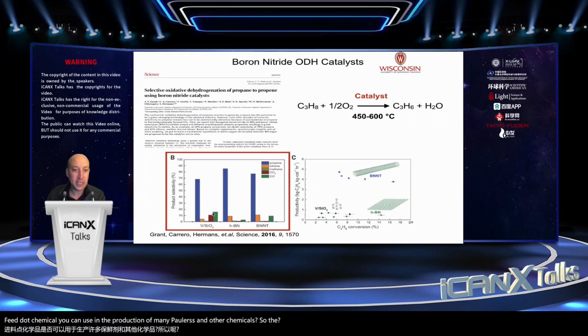So the state-of-the-art catalysts in this field were vanadium dispersed on silica. The problem with those materials is you get these unwanted CO2 and CO over-oxidations that occur. And the reason the HBN and boron nitride nanotube materials are much better is they basically don't over-oxidize appreciably. HBN in particular was much more selective. So you get this very high yield of alkenes. And so this is very great.